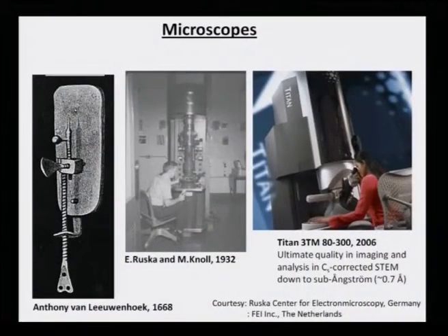We are using the Titan microscope, which is now sold across the whole world by FEI. One can reach a resolution of the order of less than 1 angstrom. As I mentioned, although the theoretically possible resolution in a transmission microscope is 1 picometer, we can never achieve it because of the problem of lenses. By correcting different lenses, it is possible to have a resolution of approximately 0.6 angstrom, which is the best possible resolution achieved till today.